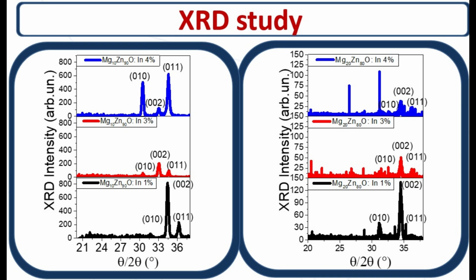X-ray diffraction diffractograms revealed a wurtzite structure, with magnesium 10% samples displaying higher intensity compared to those with 20% magnesium content. Additionally, the energy gap for magnesium 10% samples exceeded the highest value, while this value generally decreased at 20% magnesium samples. Overall, it was observed that a 10% magnesium content facilitates the enhancement of crystalline quality in the films, leading to alteration in their structural, morphological, and optical properties.